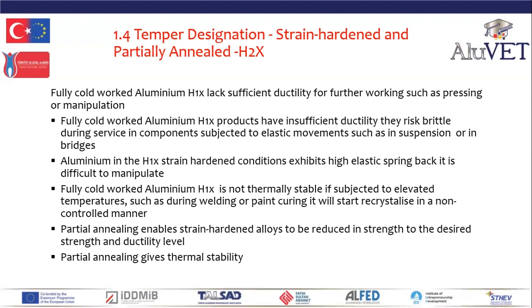Now, aluminium in the H1 strain hardened conditions exhibits high elastic spring back, so is difficult to control. And fully cold worked aluminium in the H1 condition is not stable if subjected to elevated temperatures such as welding or paint curing, as it will start to recrystallize in a non-controlled manner.